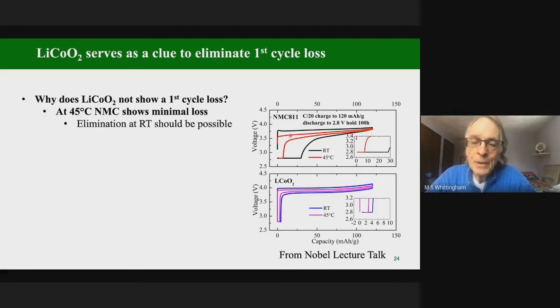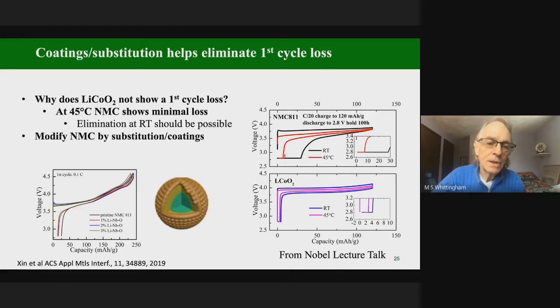So we feel that if we can modify the behavior of this 80% nickel to behave more like lithium cobalt oxide, we should be able to do this by substitution or coatings. We should be able to reduce this first cycle loss. And this is what we've been doing using a little bit of niobium. So we put 1%, 2% of a niobium solution on our meatballs, heated these up, and then we coat the surface with a lithium niobium oxide film, and it diffuses a few nanometers into the material.